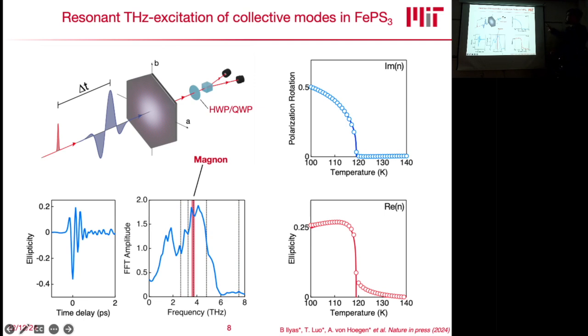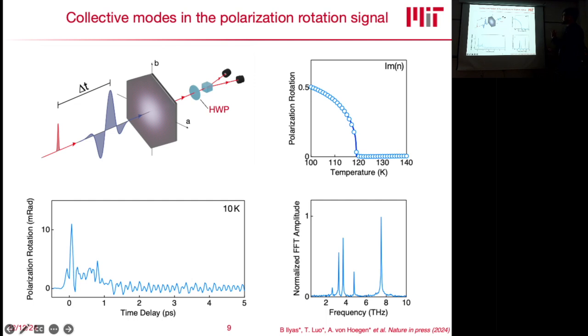So now this is ingredient number 3. We are able to excite these modes with our terahertz light. They should show strong coupling to one another, and we can probe the response of the material with our laser pulses. And just to jump right in, this is one of our time-resolved measurements taken at 10 Kelvin, measuring the transient change to the polarization rotation. As you can see here, once our terahertz pulse arrives, we get this very strong peak, which is a terahertz Kerr effect, which is then at longer delays followed by these rapid oscillations.